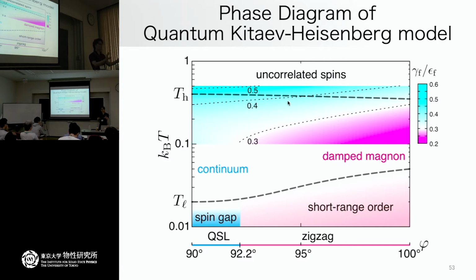If we have Kitaev coupling and gamma coupling together, then we have some spin gap behavior, or we have strong anisotropy between in-plane and out-of-plane. It's kind of XY-like, so that we can have a spin gap at the M point. But this gap size is quite different between the ab initio model and the experiment. If you calculate the ab initio spin excitation spectrum using linear spin wave, it's okay. It's comparable with the experiment.